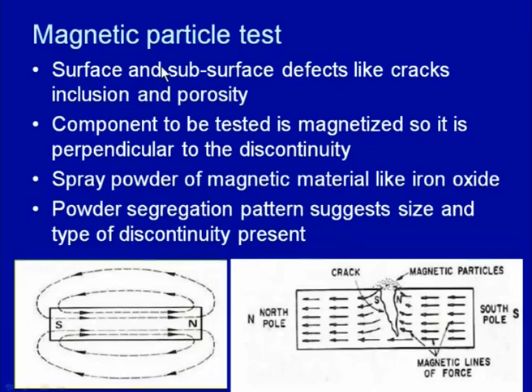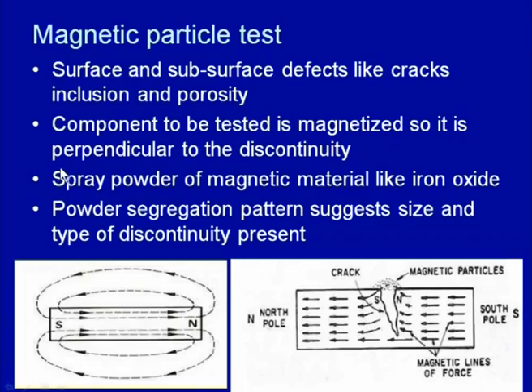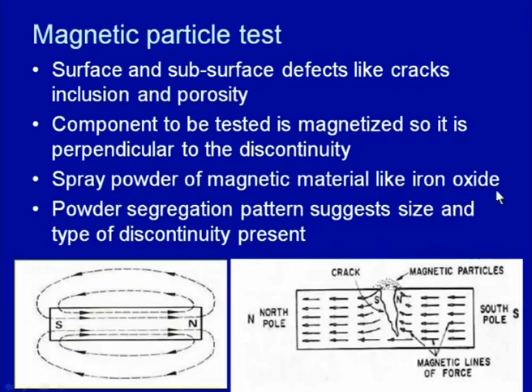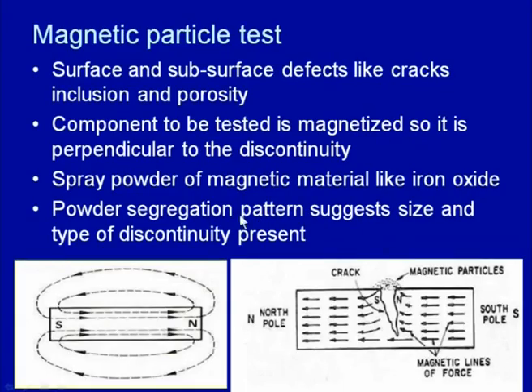And then another non-destructive test is the magnetic particle test, and this test is used for both surface as well as subsurface defects like cracks, inclusions, and porosity. In this test, the component to be tested is magnetized in such a way that the magnetic field is perpendicular to the discontinuity. Thereafter, magnetic particles like iron oxide are sprinkled over the surface, and based on the pattern of the powder segregation, it will indicate the size and the type of discontinuity which is present.